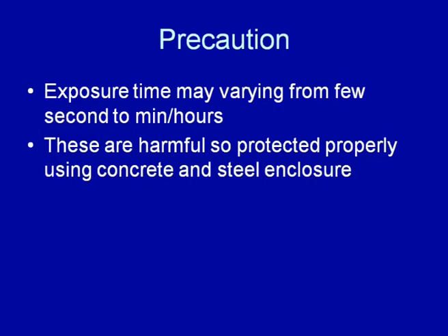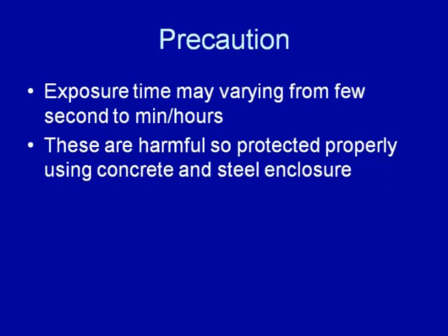This kind of test can be conducted by giving an exposure of a few seconds, a few minutes, or a few hours. Like, the gamma ray test is conducted for longer durations, while for the X-ray test the exposure is given for only a few seconds. So, X-rays are more useful for thinner components or thinner sections, while gamma rays are used for heavy sections. We know that all these radiations are very harmful to people.